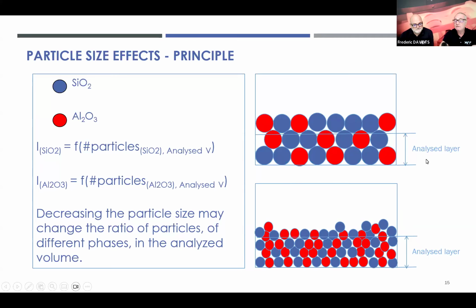And this analyzed layer depends really on the element that we are analyzing. Sodium is a light element, so the analyzed layer may be very small, maybe just a few micrometers. And for heavier elements, for example iron, this analyzed layer may be deeper. Anyway, when I reduce my grain size, it may happen that the relation between the aluminum oxide and the silicon oxide particles changes.